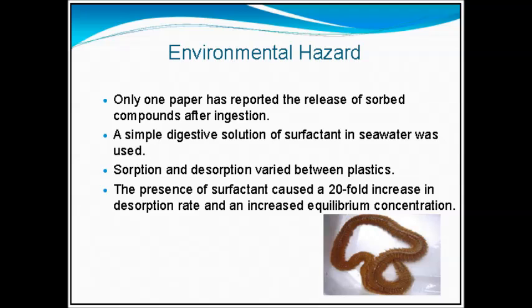So only one paper has reported release of sorbed compounds after ingestion. A simple digestive solution of surfactants in seawater was used for this and showed that absorption and desorption varied between the plastics that were contaminated with other hydrocarbons. So the presence of the surfactant caused a 20-fold increase in the desorption rate at an increased equilibrium concentration. So you could expect that, for example, in the waters that go out of the creeks here in Anchorage, we would expect the plastics to be carrying contaminants from these road hazards that are running down the drains. They would be assimilated into the plastics, carried out and get out into the inlet. Of course, along the way, they probably would be consumed by juvenile salmon and so forth, because a lot of our streams still do contain salmon at this point.